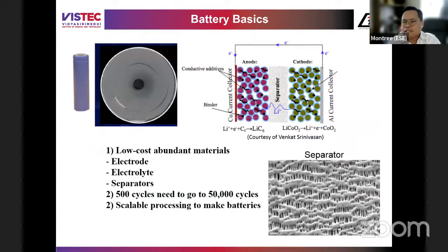Look closely here, graphite and cathode, right? But actually we have a separator in the middle. It is polypropylene or polyethylene, can be single layer or triple layer. And there it can absorb the electrolyte, the salt. So in a single cell, we have like 4 or 5 grams of electrolyte. And then we need at least 500 cycles to 50,000 cycles, depending on the application and the cathode material.